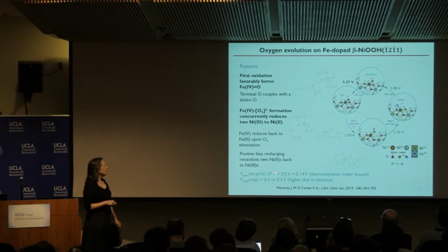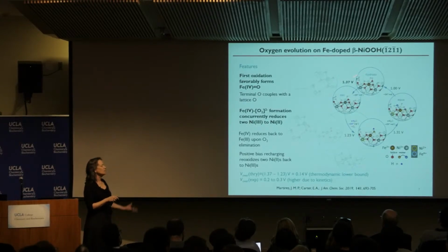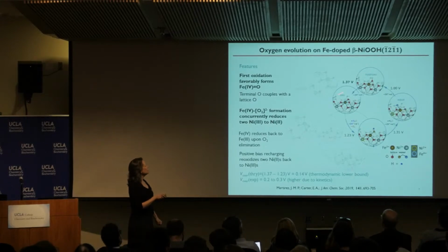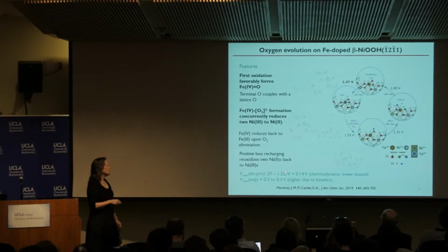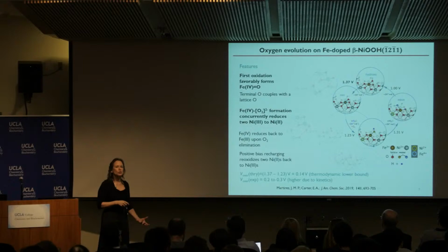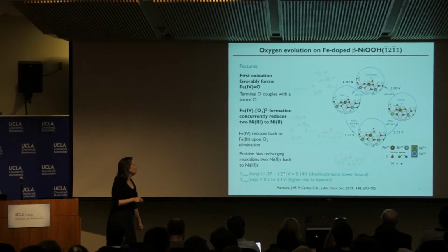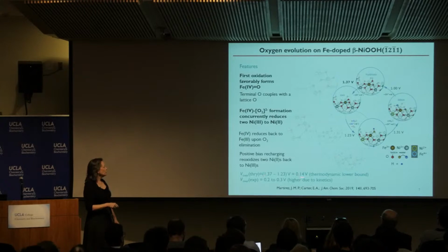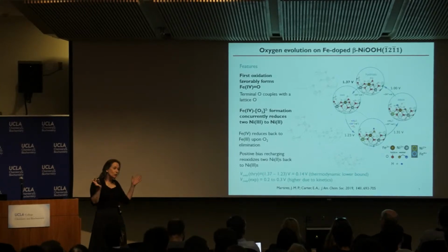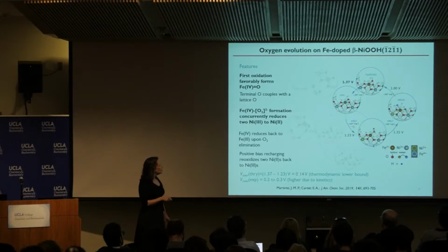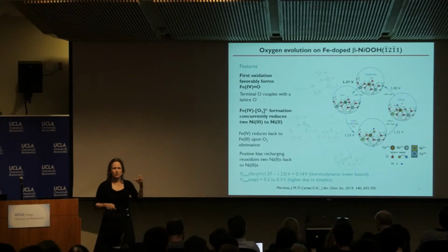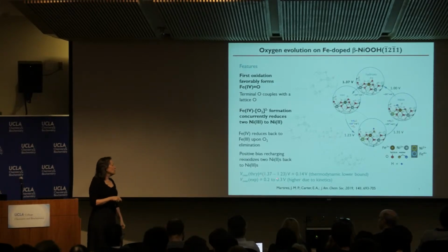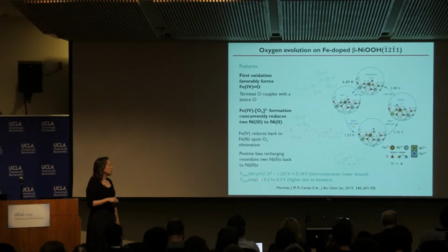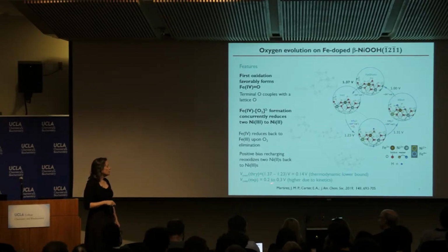And from theory, you get the overpotential by taking the highest, so kind of like the rate limiting step, the highest barrier, but this is thermodynamics, so it's the highest free energy change, the highest voltage, and subtracting off the thermodynamic potential, which, as many of you probably know, is 1.23 volts. And that leads to an overpotential that is the lowest that has been predicted ever, and it's 0.14 volts. And what that gives us, because this is all thermodynamics, is a thermodynamic lower bound. And the beauty of what Mark did is that if you compare that to experimental values for these iron-doped nickel oxyhydroxide, they are higher than that.